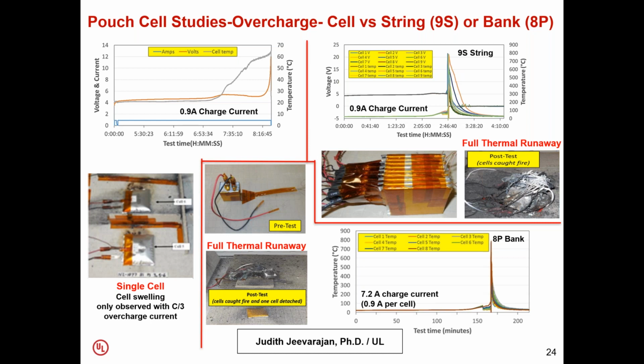But when we overcharged it with a C/3 rate current, which was 0.9 amps, we found that the cells just swelled. And so we took that same equivalent current and tested it with a string of 9 cells and a bank of 8 cells. And in both cases, we found that all the cells went into catastrophic thermal runaway with a big fire. And as you can see, post-test, there was no cell left behind.